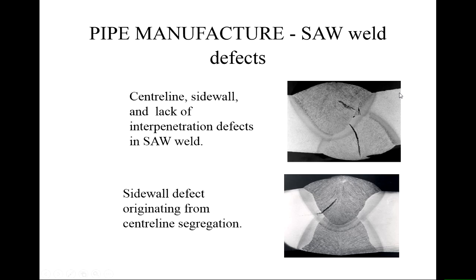At least if I look at that, you might say actually the external one was done first and the internal one was done second, and that may be the issue in this case, but this is probably a special sample to make defects. So you've got a defect in here and you've got a crack in here. So these are center line and sidewall defects. So this probably is where this weld is a bit offset compared to this one. So you've not quite got enough heating of the material here.